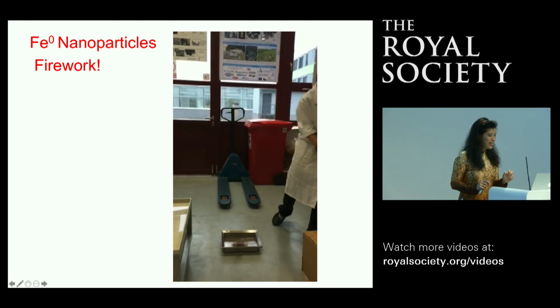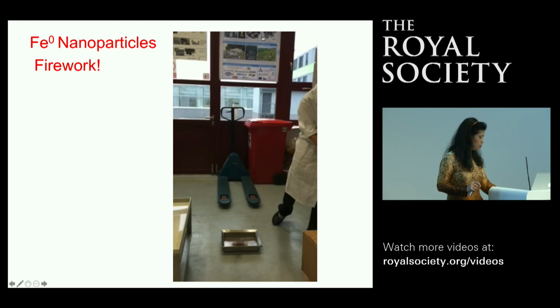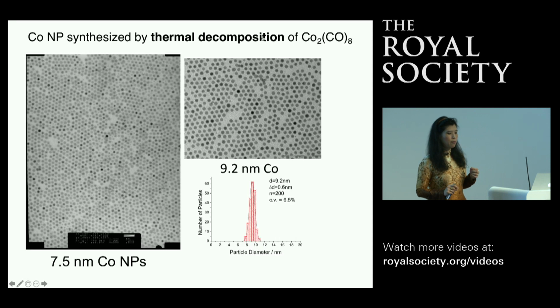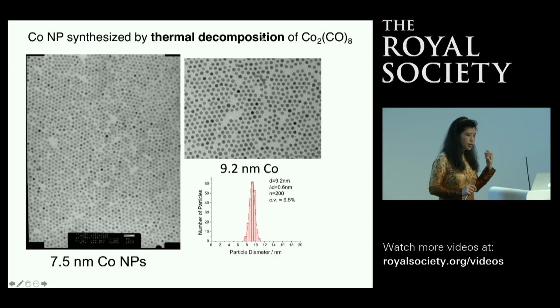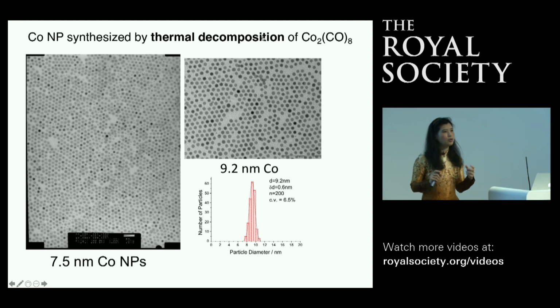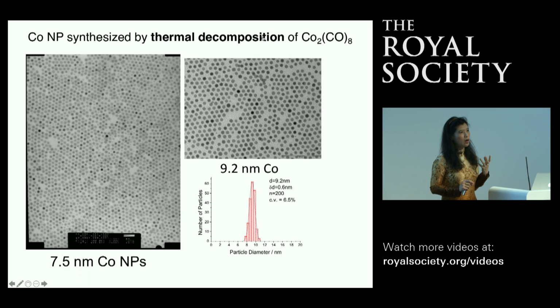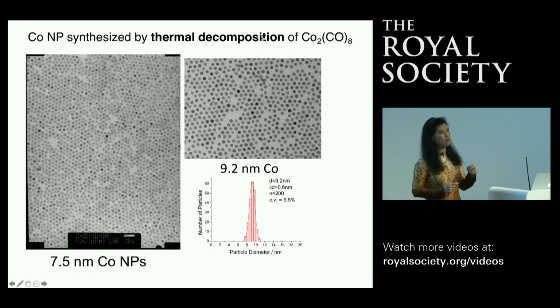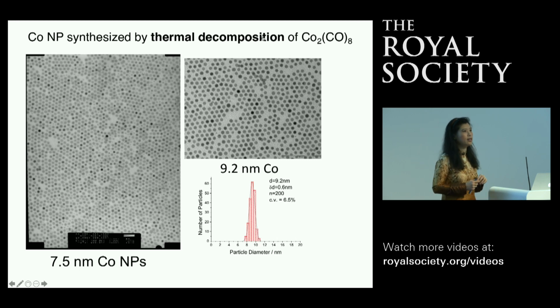Wow. So you can see that the iron, zero valent iron, will burst into flame. So it was too difficult for me to make the iron. So we made cobalt nanoparticle. I could make beautiful cobalt nanoparticle, but it's in organic solvent, so it was not really useful. Then we made them in peptide and dispersed them in water. But later on, 2 days later, it turned into emerald blue. Very beautiful, but totally useless. Because you change from the ferromagnetic into the antiferromagnetic stage of the nanoparticle, and you lost the magnetic property entirely.